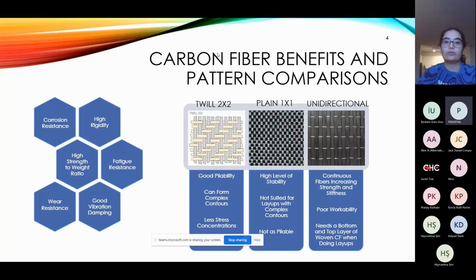We selected a 2x2 twill weave pattern as the most suitable pattern as it can conform to complex contours, has good pliability, and few stress concentrations. It also has great functionality, moderate stability, and formability. Another pattern is the plain 1x1 weave, which has a higher level of stability, but is not as pliable nor as well suited for layups with complex contours. It also has a lot more crimps that create stress concentrations and weaken the weave over time. The third pattern I would like to highlight is the unidirectional pattern, which is oriented in one direction, so you can tailor the layup however you'd like. However, it tends to fall apart and hence has poor workability, and it usually needs a bottom and top layer of woven carbon fiber when doing layups.